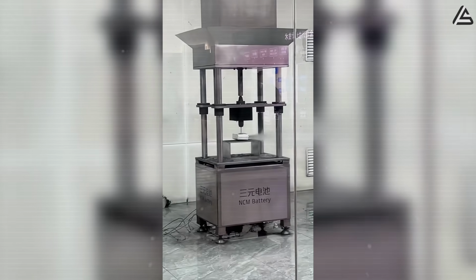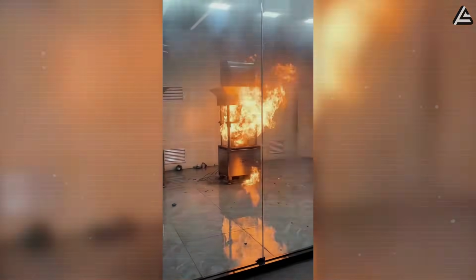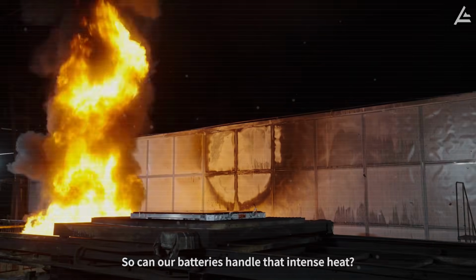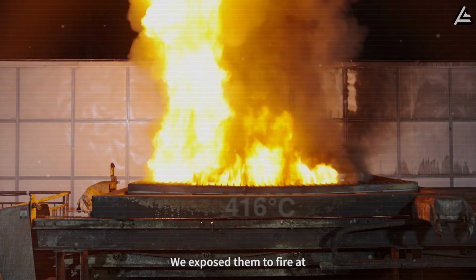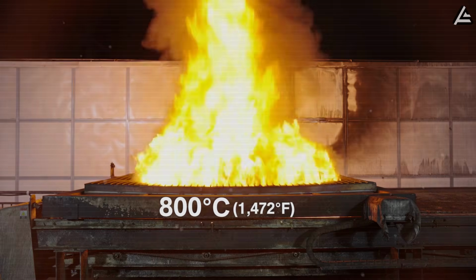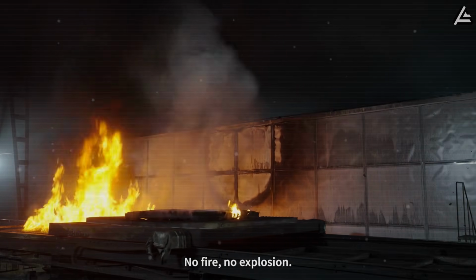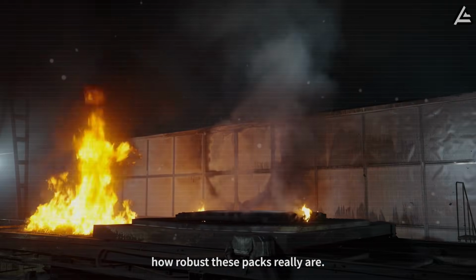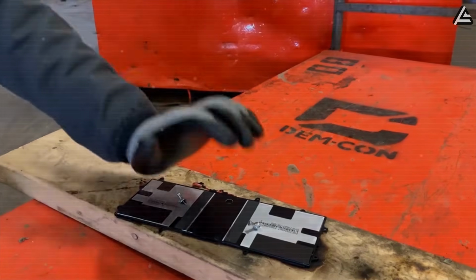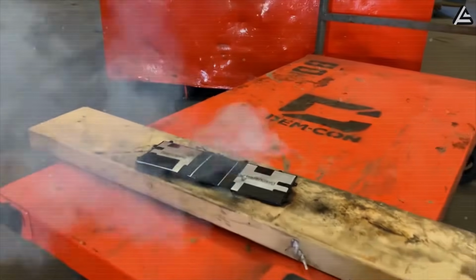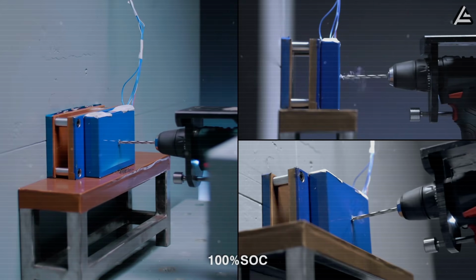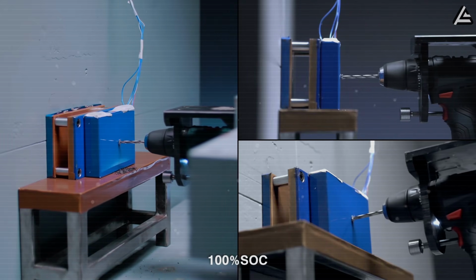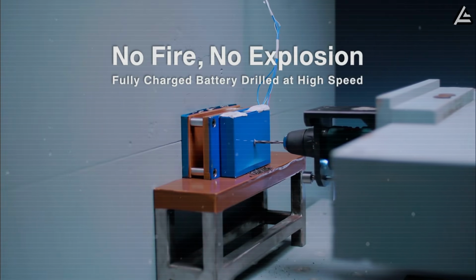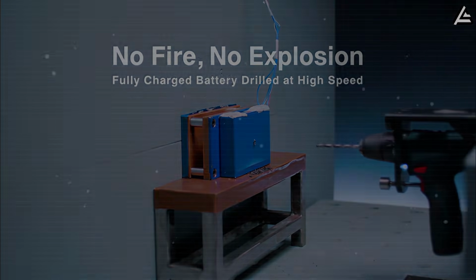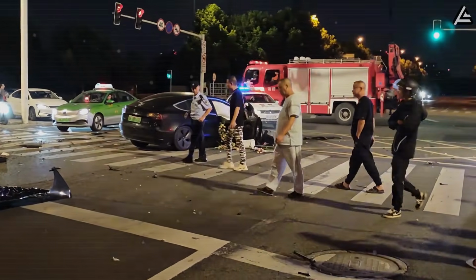Once runaway begins, a lithium cell can soar past 500 degrees Celsius in under a minute, while sodium-ion prototypes in abuse testing often plateau well below 300 degrees Celsius, dissipating energy without crossing the ignition threshold. Crash simulations highlight another key difference. When punctured by a nail or compressed under mechanical force, lithium-ion cells tend to vent flammable electrolyte and ignite almost instantly. In similar tests with sodium-ion, the cells frequently bulge, leak, or drop voltage but fail to produce open flames. For a driver, that translates to a disabled car rather than a fireball.